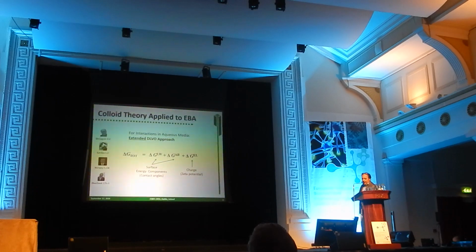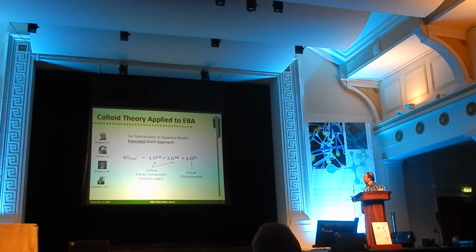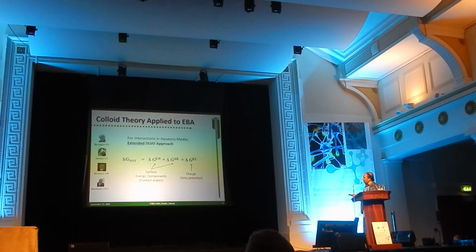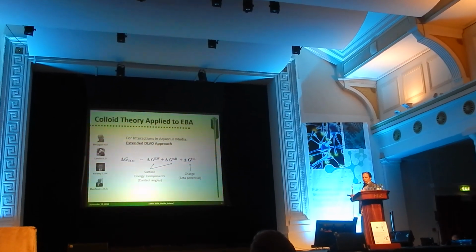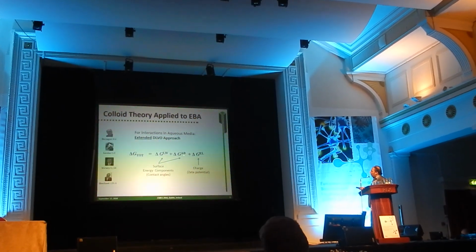So in this extended DLVO approach, we are looking at three different components. These components are related to Lifshitz-van der Waals forces, acid-base forces, so electron donor and acceptor ability of the interacting bodies, and of course net charge.